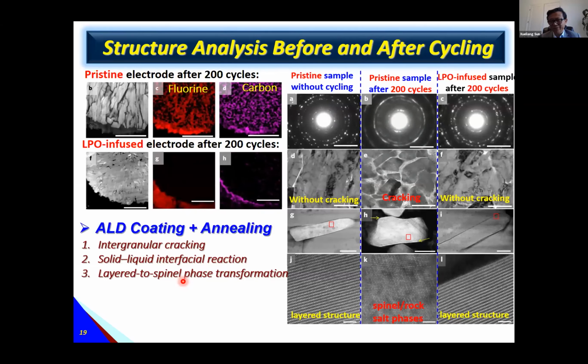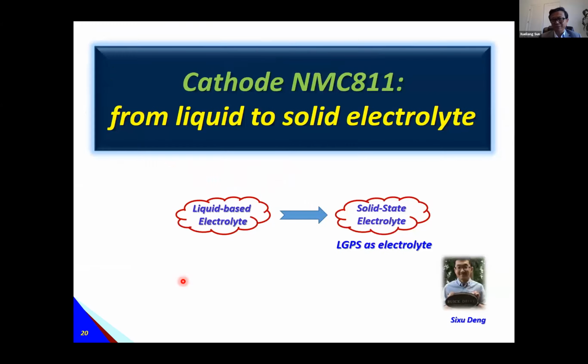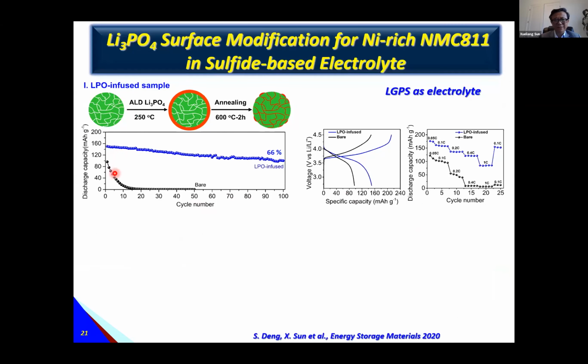If we use the same system for solid, for example using LGPS as an example, using the same procedure, what happened? Without coating, the battery cannot cycle. But with ALD coating and annealing, the battery with the LGPS solid-state electrolyte can cycle, but it just maintains 66% retention. We still found there's a big challenge compared to liquid.